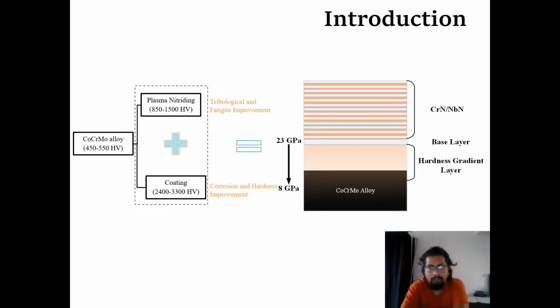Inside the chamber there is a plane surface which acts as a substrate holder, and this substrate holder acts as a cathode as well. So you apply a negative potential at your substrate and positive at the chamber, and then you generate a plasma DC discharge on it, and plasma nitriding happens. But plasma nitriding by itself is not proven to be effective, so it needed more.